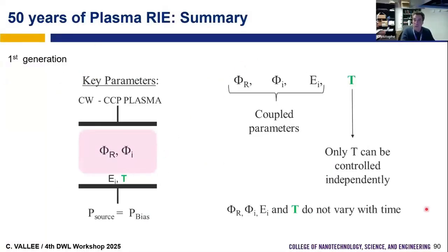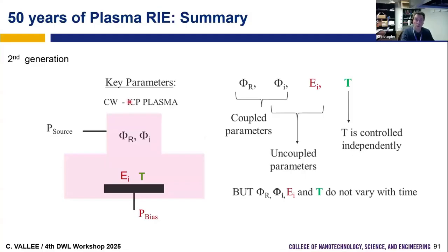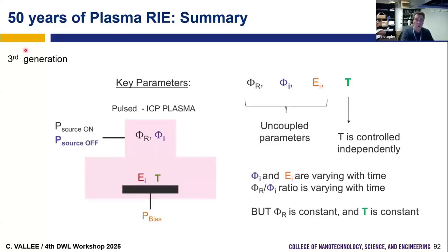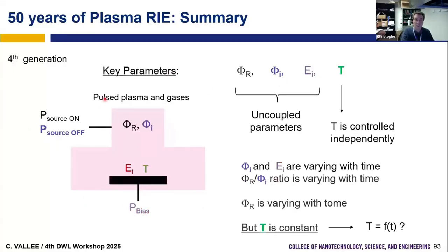So to conclude, this was the first generation of plasma etching reactor where all was coupled, nothing was varying with time. After, we used a second generation like dual frequency and HDP source to uncouple two parameters, but still all was fixed, not varying with time. After, we had the third generation when we pulsed the plasma to uncouple all parameters and to vary with time the ion flux and the ion energy and the ratio between the radical flux and ion flux. And the last generation, where we pulse not only the plasma but also the gas. So now also the radical flux is varying with time. But still the temperature is constant.